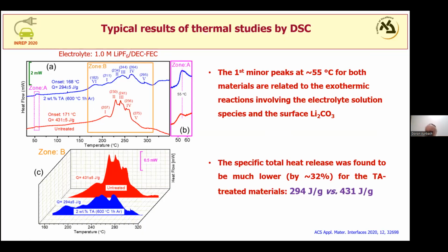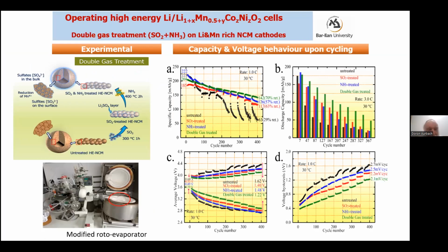Now let me move to another example. Another example here, we did gas treatment. It appears that when you heat this material with this stoichiometry in an atmosphere of SO2 or ammonia, you change the surface. You strengthen the surface. There are compounds which are formed on the surface. In the case of SO2, there are sulfates and sulfides, and they form networks. So we have protection. We have a buffer zone, but we have also good transport of lithium ion through the films.